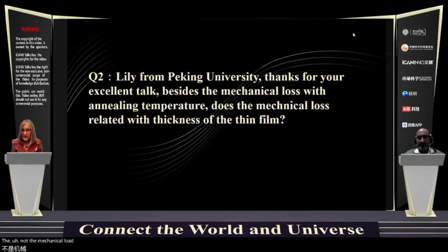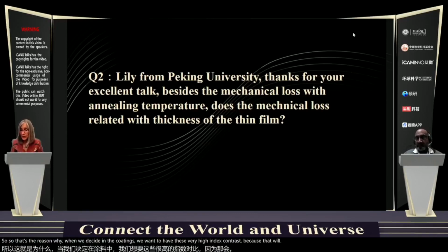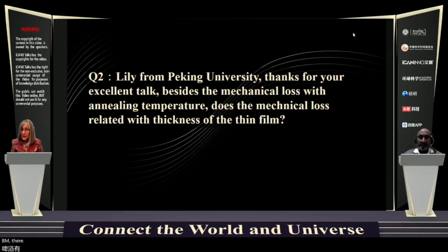The mechanical loss is actually not related to the thickness of the thin film. Just to give you an idea, we normally grow the thin films in which mechanical loss is measured about 500 nanometers thick, and we do that because this is what our colleagues at LIGO need. Mechanical loss arises from energy dissipation. Now, Brownian noise will depend on thickness, yes. So that's the reason why, when we design the coatings, we want to have this very high index contrast, because that will actually reduce the overall thermal noise or Brownian noise in the coating.